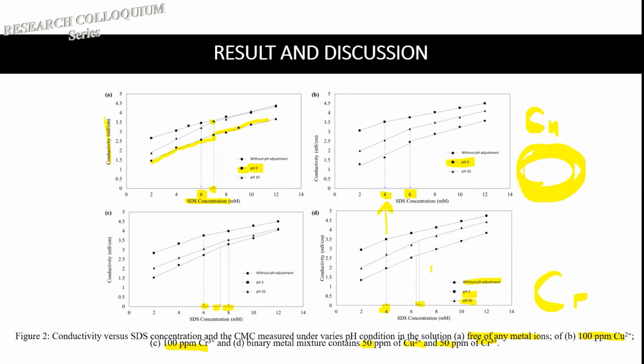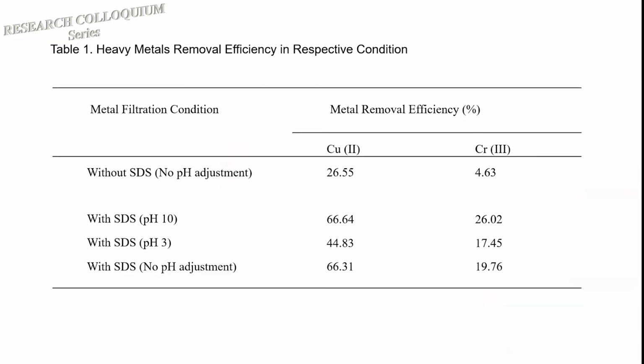So by getting this result, we further proceed to the filtrations. As expected, if we do not put in any SDS, it's very obvious that the rejections for both metals could be very low, 27 and also 4% only. But with the presence of SDS, the rejections for both metals are greatly increased. For example, at pH 3, we observe that the rejections could be somewhere around 45 and also 17 for copper and chromium respectively. The rejections actually is the lowest among all another 3 different pH.